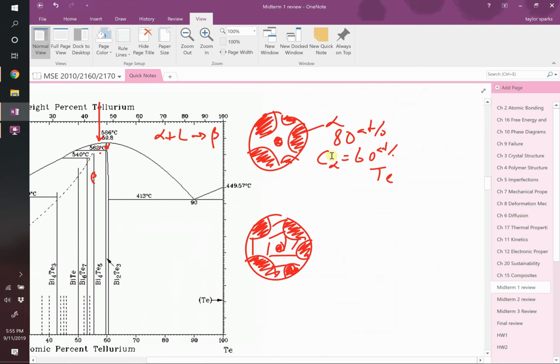Lauren: Would the lamellar structure still form even though, in the alpha plus liquid, you're only forming beta? Like, in there you drew new alpha. To make the lamellar structure, you have to have more alpha form, but no more. Oh, I see the problem. Well, we know that we have 50-50 after, but we had 80% alpha before, so you're right. That actually may not be quite as lamellar as it looks. It might be mostly beta in between, and your alphas would shrink a little bit.